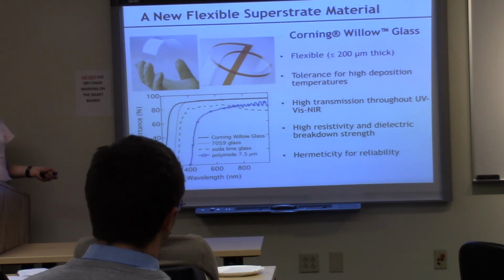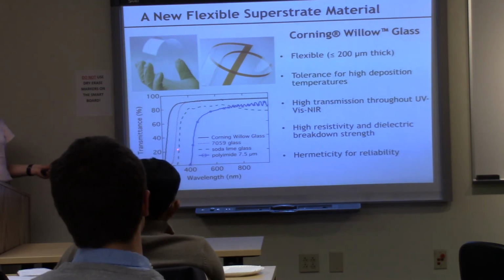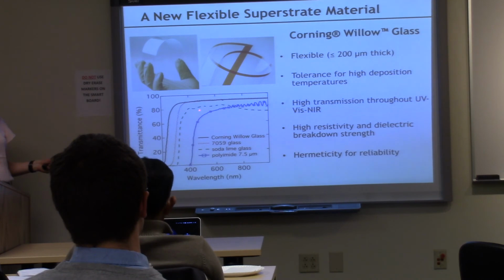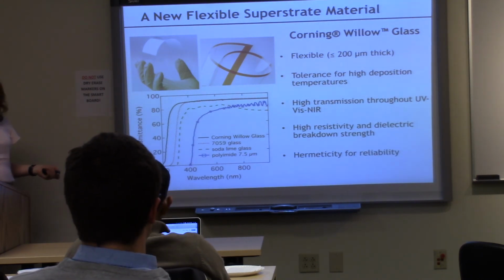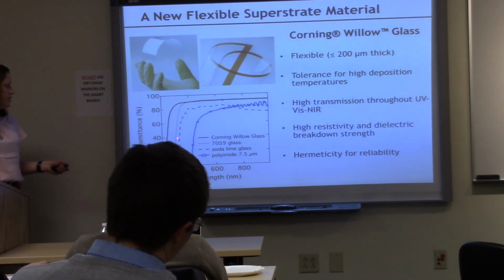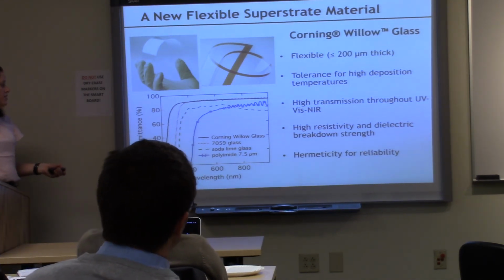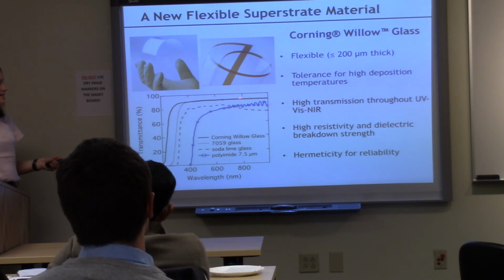You can see that that cuts off even earlier, or excuse me, that has an even lower wavelength cutoff, so the transmission on that is actually very, very good. This difference practically doesn't matter too much for solar just because of where the energy is coming in on the spectrum. But this black line here is the Corning Willow glass, and here you see you just get exceptional